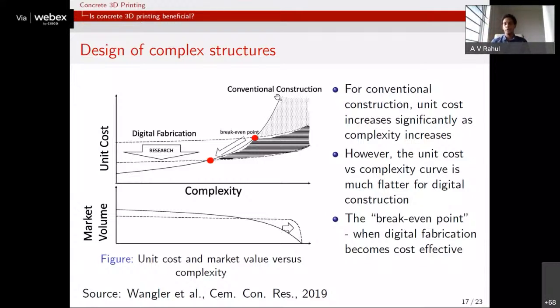That's because you have to have a form to do this type of structure, and then the formwork cost significantly adds to the total construction cost. But when you have digital fabrication or a 3D printed structure, you don't have that significant increase even when the complexity of the structure increases. So there's a break-even point, and above that you can see that conventional concrete is significantly more expensive than concrete made through digital fabrication.